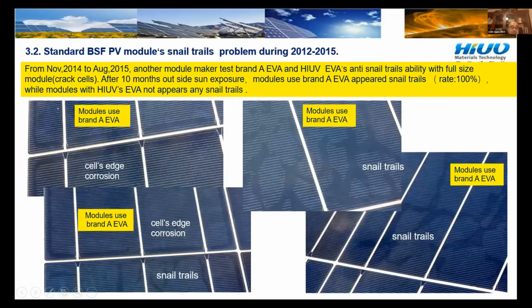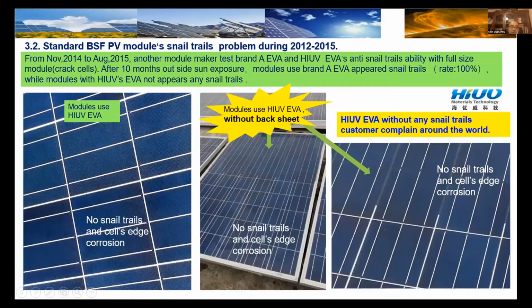This is the test result. Okay, they used some EVA that is really sensitive to snail trails. You can see from the edge, all snail trails. Some cracked areas are really serious like this. Okay, this is the same period using HIUV EVA, also cracked cells. You can see no snail trails and even no cell edge corrosion. And here they even made a module without backsheet on the backside. Okay, they still did not find any corrosion issue here.